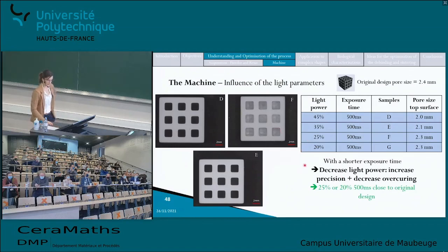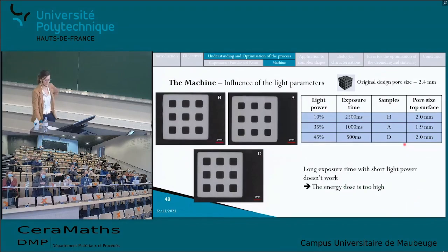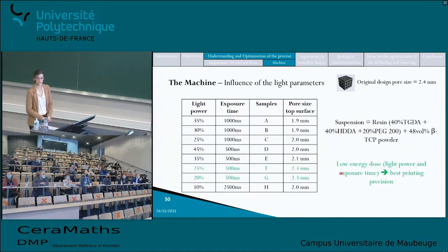And when I evaluated the last sample, sample number H, with a very long exposure time but a very low light power, it was not better than the other samples. So here, the long exposure time with a low light power doesn't work. The energy dose seems to be too high to be printed with the composition of my suspension. So actually, the best energy doses were 25% of light power combined with 500 milliseconds, or 20% of light power combined with 500 milliseconds of exposure time. That enabled the best printing precision.